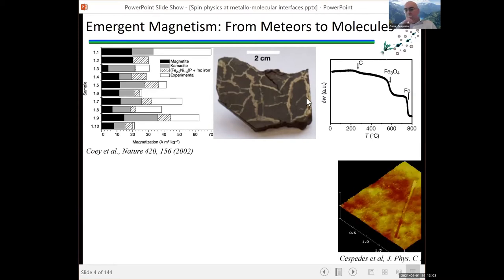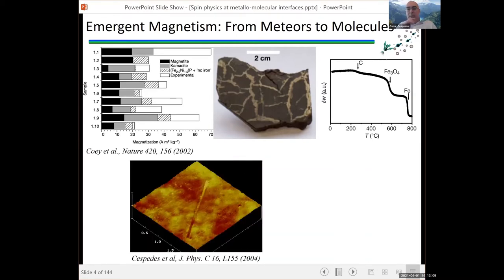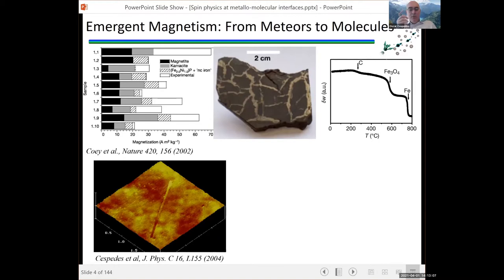So then we started to do experiments in thin films and molecules, and that's why I started in this topic. What we did is place carbon nanotubes on ferromagnetic substrates and take some magnetic force microscopy images. And what we saw is that there was a magnetic contrast, a stray field emerging from these carbon nanotubes, independent from the magnetic substrate underneath. So we were indeed inducing magnetism in these carbon nanotubes.